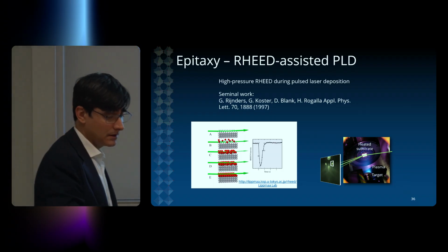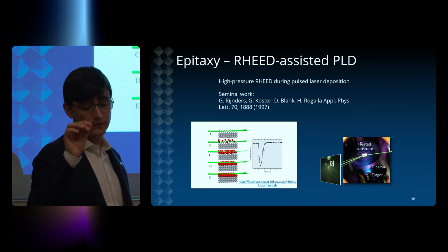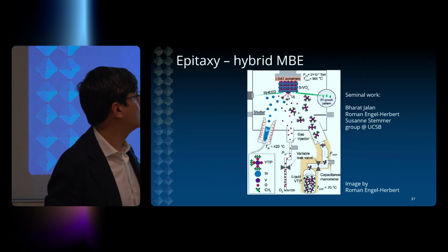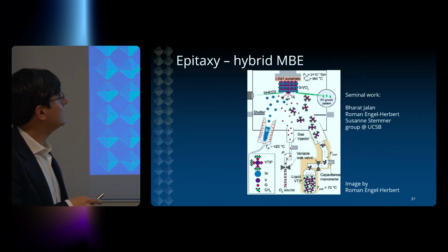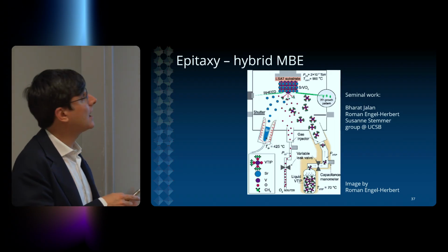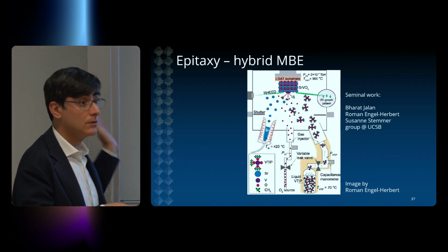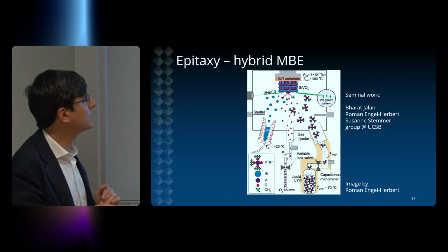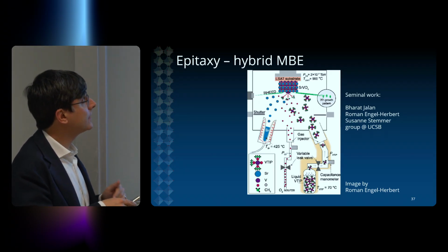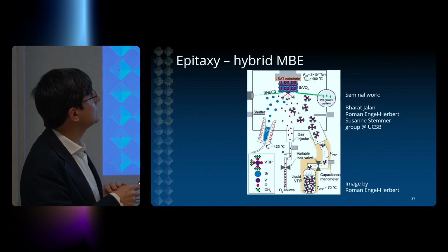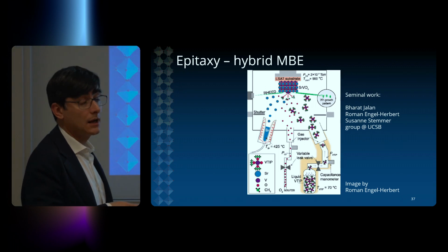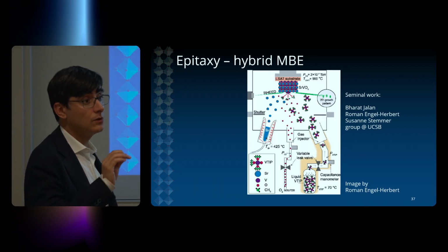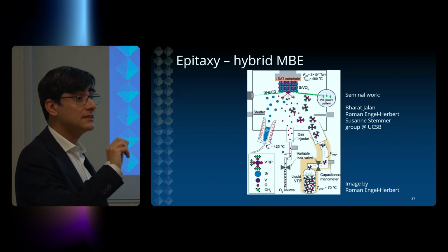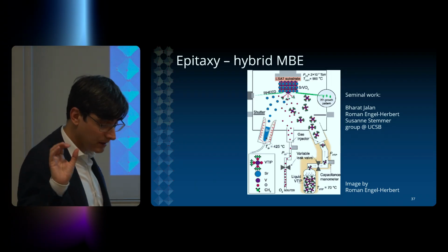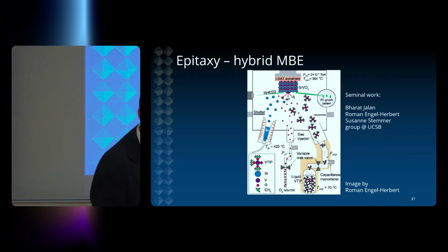So this is something that allows you to really count the number of layers of atoms that you're putting on top of a crystal. And the new kid on the block is the hybrid MBE approach. This is something that we have built here in Geneva, and we started working with it. It's an innovative way of building materials based on molecular beams. This would allow us to have very exquisite control on the stoichiometry of these materials, to minimize the number of defects, and to have interfaces that are absolutely atomically perfect.